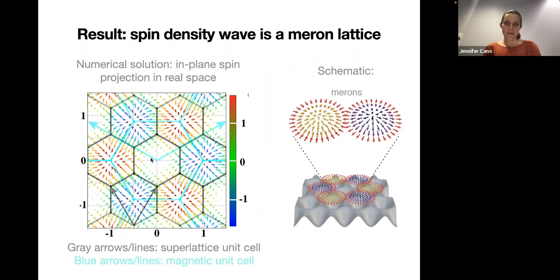And it's also pretty unusual because merons don't occur very often in nature. Skyrmions occur more often because they have a quantized topological invariant, but merons don't have that property. But this system has a lot of extra symmetry. And so what happens is that along these certain mirror planes, the spin is actually always pointing in plane. And so that's actually, I think, what stabilizes this meron lattice.